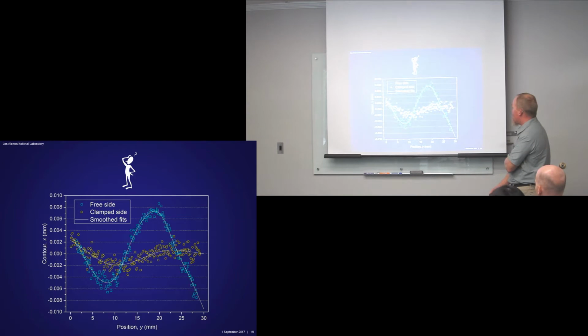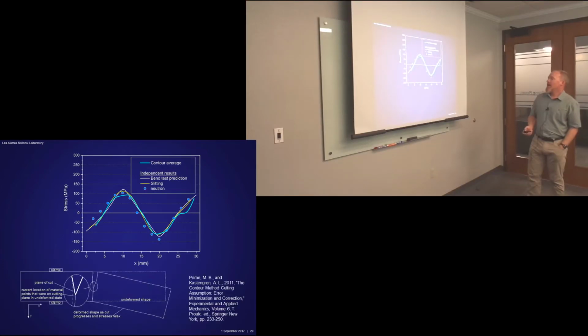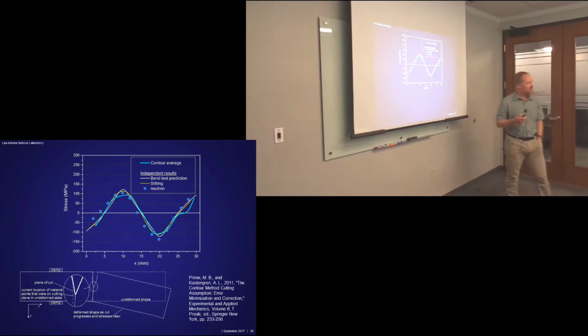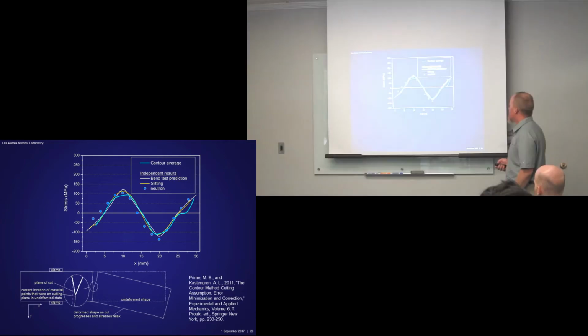So finally I went and grabbed the second half of the beam and brought it to the CMM shop, and I got this result here. Not very much displacement, not much shape. Once I averaged the two sides, I got the cyan curve, which is pretty close to the results we expected. And of course, we figured out, I had a grad student back then. We didn't publish this for a long time, but right away we did this calculation and figured out if you unclamped on one side, how much the part moved and how much that would mess up the contour. So it made sense. We understood it.